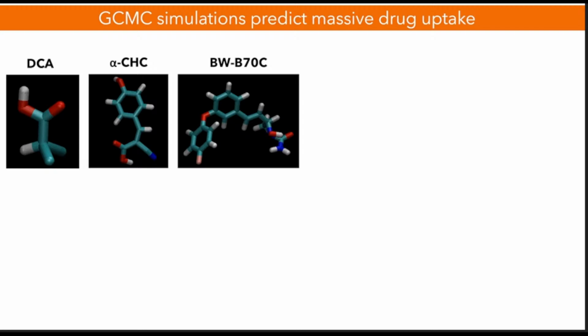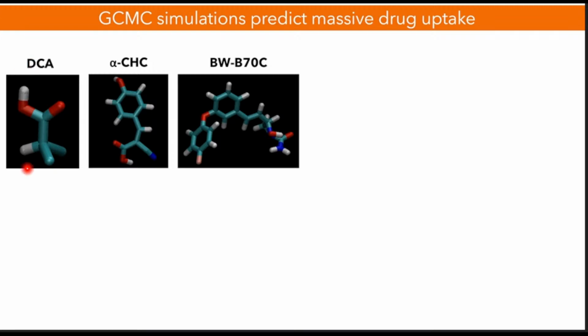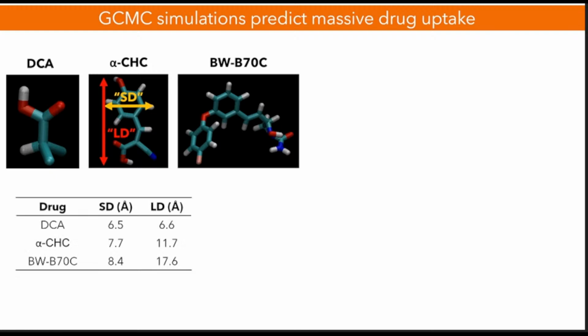So this is for ibuprofen, but we are more interested in real drug molecules, and in particular cancer drug molecules. For chemotherapy, we have this very simple one, DCA, which is not really a cancer drug, but this alpha CHC and this other more complex, highly hydrophobic one are real drugs, including a standard of care drug that you can find in a lot of different papers in the literature. We pay attention to the sizes of these drug molecules. This is the largest size, and this is the narrowest, the smallest size that we can have in this material.